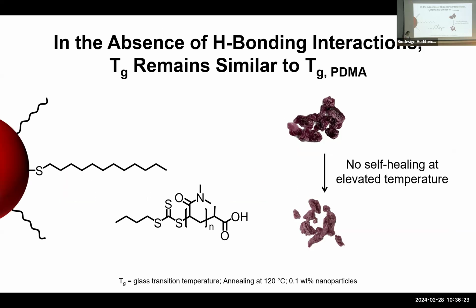This is one of the bulk properties that people analyze using these polymers. When you don't have those interactions, the glass transition temperature doesn't change. But when you have these nanoparticles with the carboxylic acids, we do see an increase in glass transition temperature.